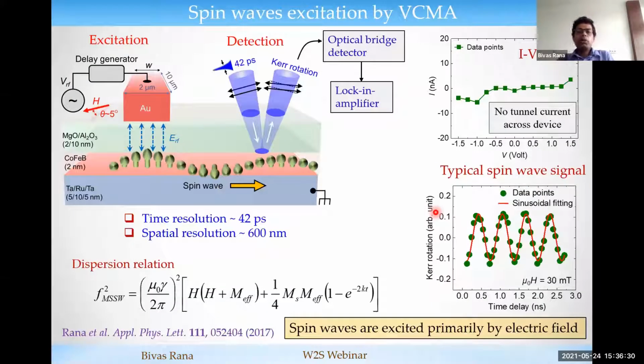So then I will talk about the excitation of spin wave. To excite the spin wave, what we did was shrink the size of the top gate electrode to a dimension of 2 micrometers by 10 micrometers. Then we applied a sinusoidal gate voltage, and that generates an electric field right underneath this gate electrode. And that electric field basically tunes the perpendicular anisotropy periodically.